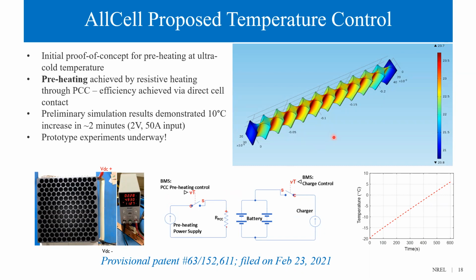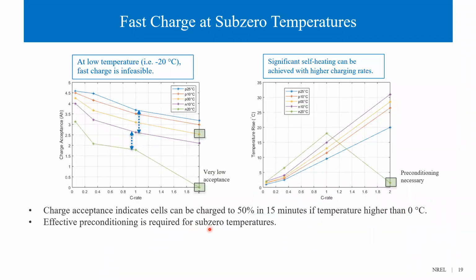Proof of concept for preheating was carried out with 3D finite element analysis of PCC. The result demonstrated nearly 10 degrees Celsius increase can be achieved in about 2 minutes with phase change composite heating. A prototype experiment is in progress. Besides study at room temperature and beyond, we have been working with AllCell to broaden this technology for fast charging at sub-zero temperatures. The first goal is to develop a baseline fast charging at varying ambient temperature.